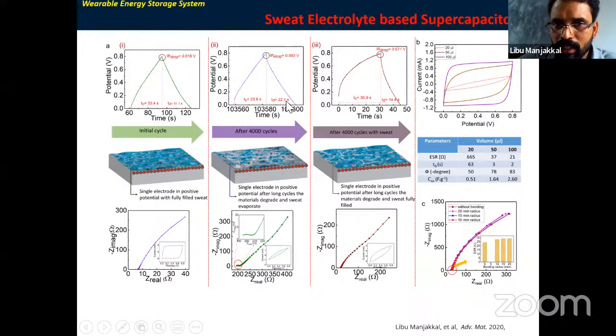And then after 4,000 cycles, I saw a sudden drop in the potential value, and you can see the variation here. Then I opened the device and checked the surface of the electrode to understand what happened. I noted that, because of the PSS, some of the material disintegrated, and there is also an issue in the coating of the material, and the electrolyte was fully evaporated. Then I dropped sweat again and studied it, and I found that the device is working again, but not like the initial cycles. This is mainly due to material degradation.